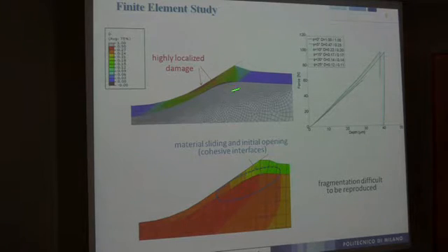We can easily single out that the most damage occurs in correspondence of the piling up area of the imprint, which is consistent with experimental observation. And here we see some compression damage due to the interaction with the indenter. And in this case, this is rather a shear induced damage. We can also represent the prevailing shearing mode that occurs at the interface between the coating and the substrate.